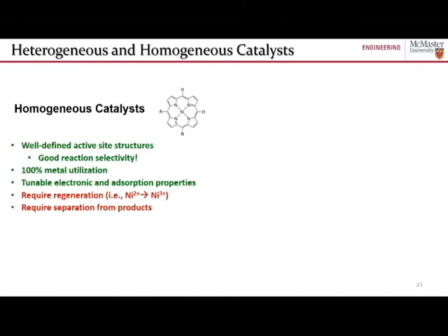Some of the attractive properties of homogeneous catalysts is the first is that they have very well-defined active site structures. You can see that molecule that I showed there. There's going to be millions of these dispersed in a mixture acting as your catalyst, every single one of them with the same atomic structure, same electron properties. And with that being said, because they are all identical, they all have identical activities and selectivities. So you can get really good reaction selectivity. You don't have all these variations in your catalyst structure and the way they interact with reacting molecules.